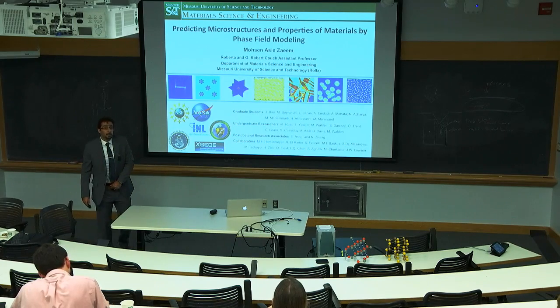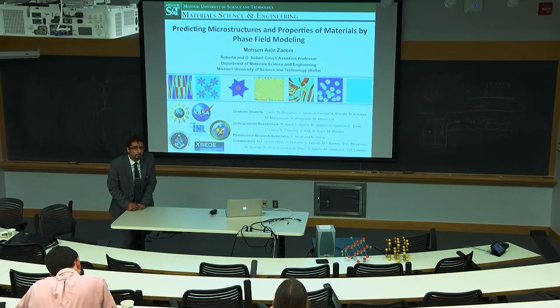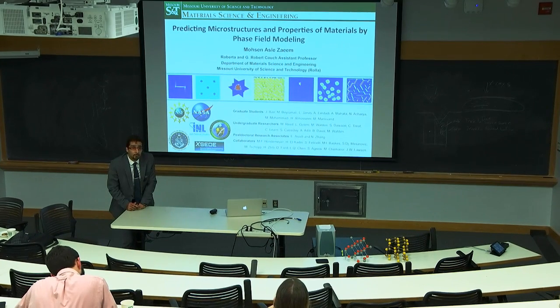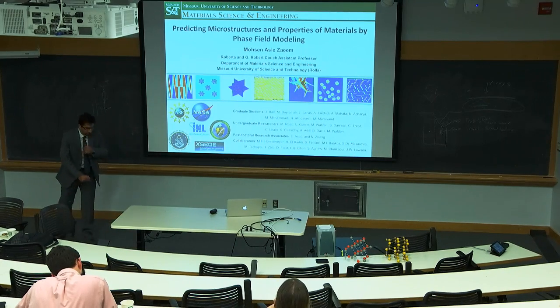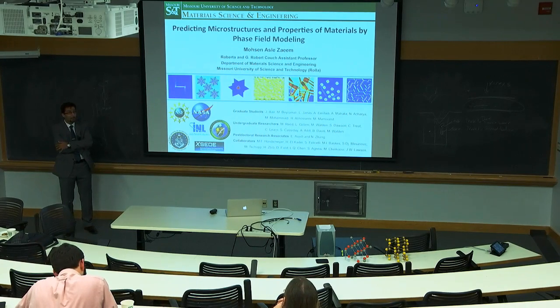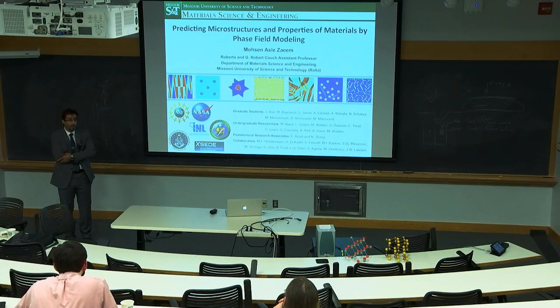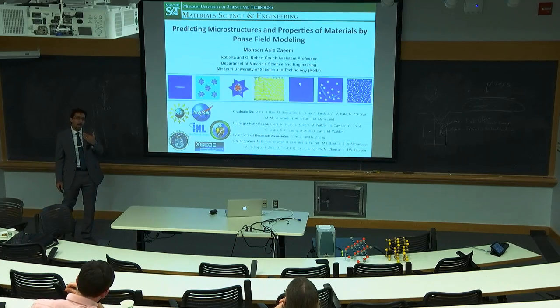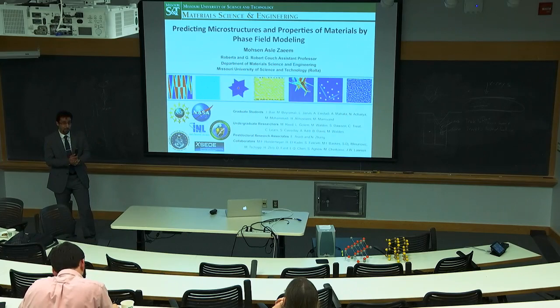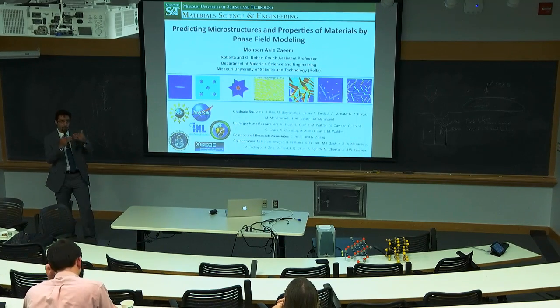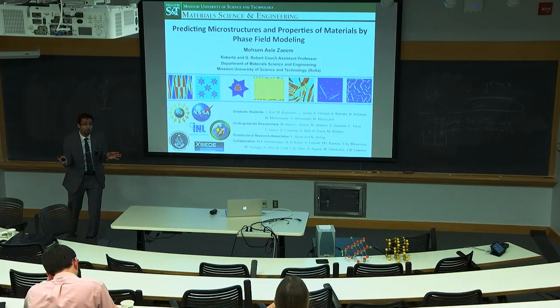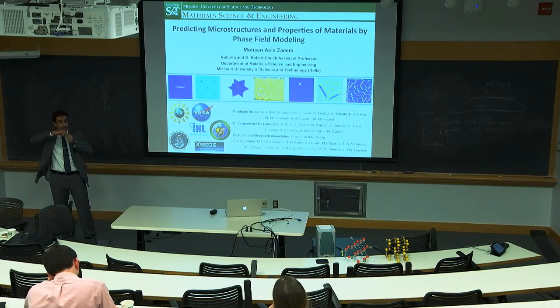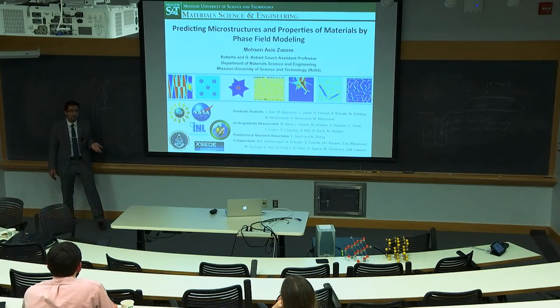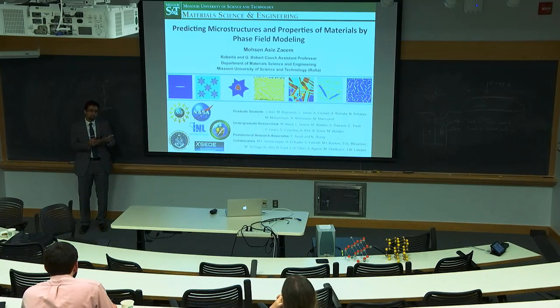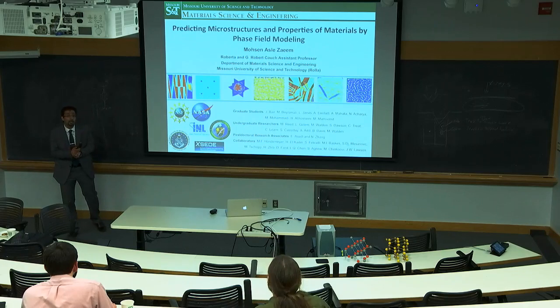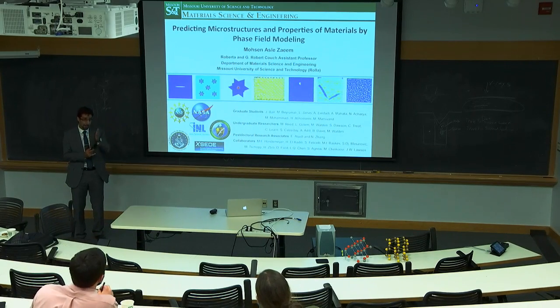Here's a question that you may know the answer to with this methodology. Many steels become brittle as you cool. Can you tell me under the conditions given whether steel will become brittle? By MD simulations, yes. By molecular dynamics, atomistic simulations, if we have the right interatomic potentials, we can study failure mechanisms. We can see the transformation from ductile to brittle. We can see the jumping in the stress-strain curves. MD simulation is one of the primary methods to capture mechanical properties, primarily for single crystals. Then we can extend it to polycrystalline materials. But atomistic simulation, molecular dynamics, is the answer to your question.